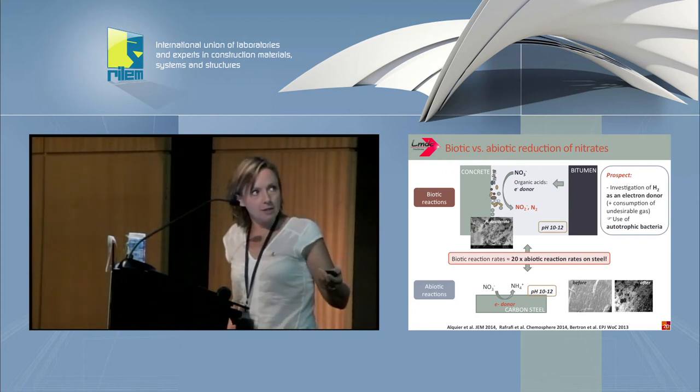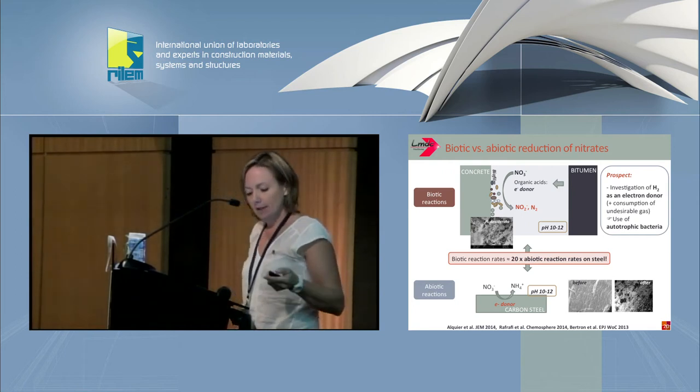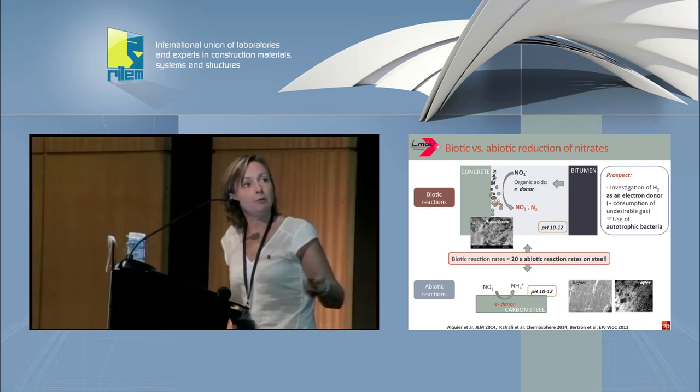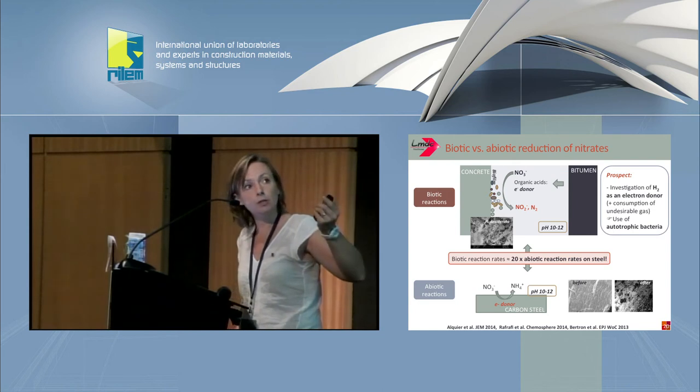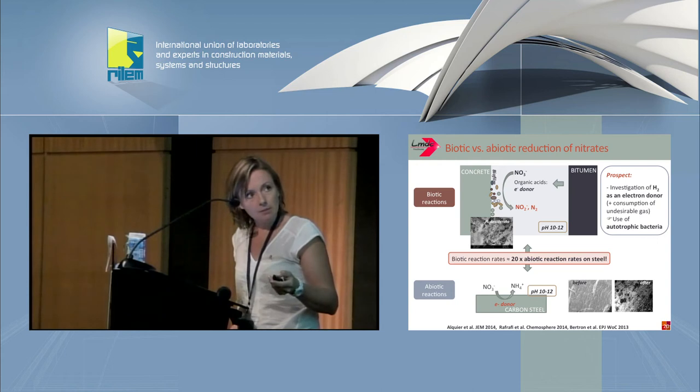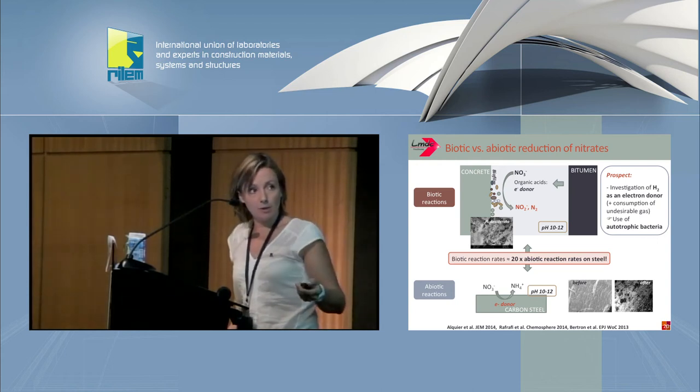We also have studied abiotic reactions using carbon steel, and we could see, without bacteria, that nitrates could be reduced into ammonium in the same chemical conditions. In this case, carbon steel was the electron donor.